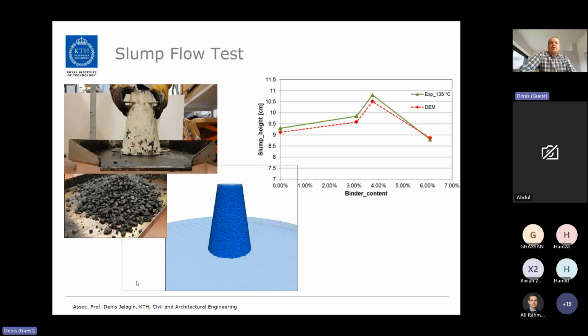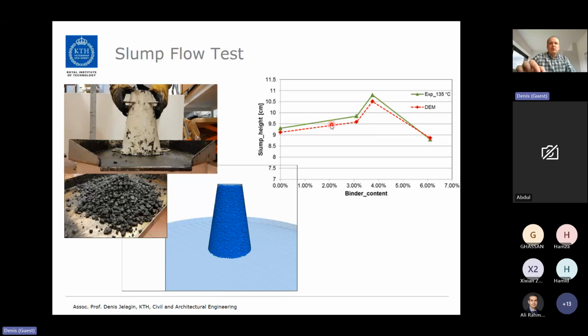Agreement between experiments and simulations is quite nice. So here the green line is the experiments at 135 degrees Celsius, and the dashed red line is from discrete element simulations. And you can see that at least we capture the physics of the process, so increasing resistance to flow and then dropping resistance to flow at further increase of binder content.